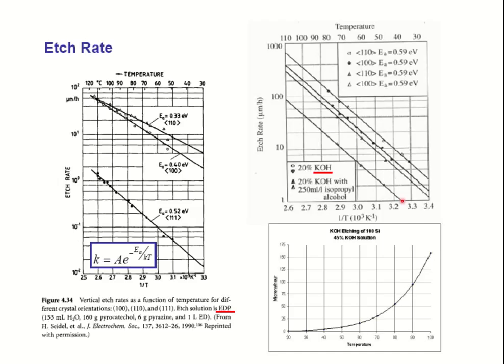I put some graphs here of the etch rate in the 111 direction, the 100 direction, and the 110 direction. It's also temperature dependent. This etchant solution is EDP. If you use EDP, the etch rate is temperature dependent, plotted against inverse temperature. So if the temperature goes higher, moving to the left, the etch rate is higher as well. This is a log scale here. So a higher temperature etchant can make the etch rate higher. That's the etch rate and temperature dependency covered here. Also, if you're using KOH, you have the same tendency: a higher temperature gives a higher etch rate.